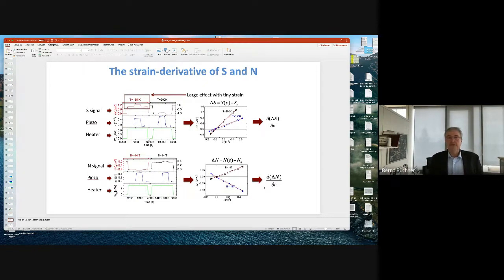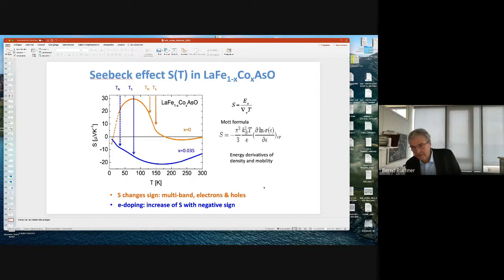So the message is, okay, even these more complicated transport coefficients, not only the resistivity, also even more complex transport coefficients, which are typically connected to the energy derivatives of density and mobility times, and that means the difference between the mobility of electrons and holes or to details of the Fermi surface, let's call it like that, even these quantities show clear strain dependence.